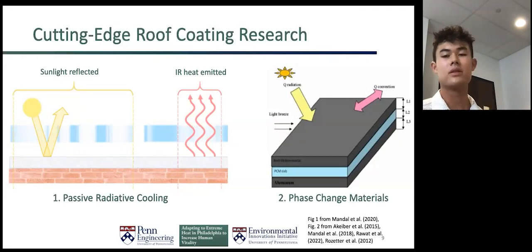And each of these have shown really impressive thermal results by converting the sunlight into latent heat instead of sensible heat, but they're limited by their durability. A lot of the phase change materials change their volume during the phase transition, which could put a lot of stress on surrounding materials, like you see in this diagram. And then also some of them are less durable and couldn't even be walked on, which really limits their use cases.